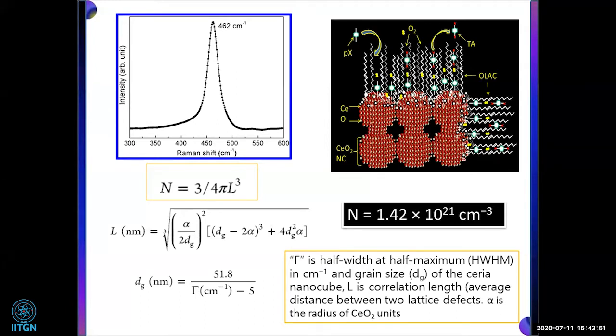So we calculated the number of vacancies. This is the equation, N is equal to 3 by 4 pi L cubed, where L is the correlation length, the average distance between two lattice defects. From this you can see, if we have more defects, this L becomes lower. And the number of vacancies we got is 1.42 times 10 to the 21 per cubic centimeter. So that means a huge oxygen vacancy is there.